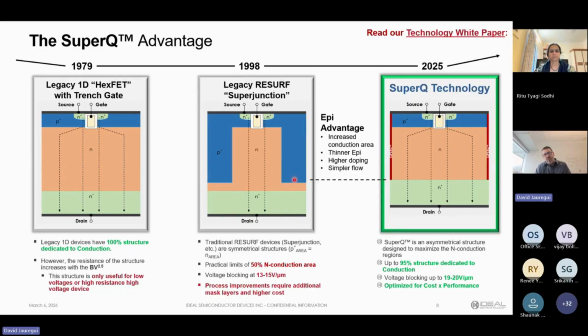And early on when this superjunction structure came out, it was in the 13 to 15 volts per micron, and they've improved a little bit since then. But that blocking capability, along with the charge compensation that occurs, is what allowed it to really make a step function improvement in RDS(on) compared to, excuse me, the HEXFET. Then came our technology. Fundamentally, at the core, we're also charge compensating a drift, but we're not relying on a P implant or P column as it is here in this symmetrical superjunction structure.